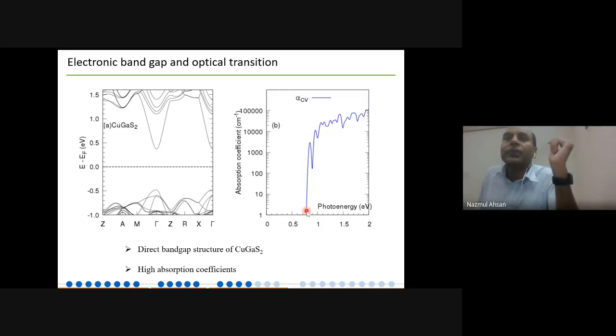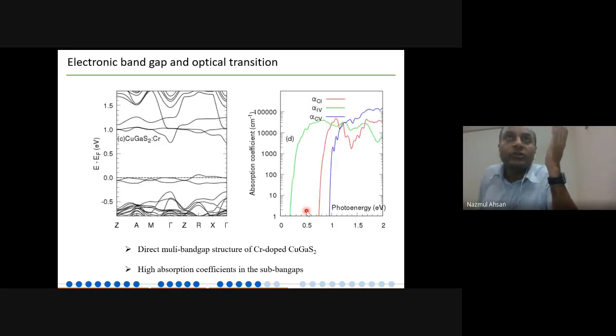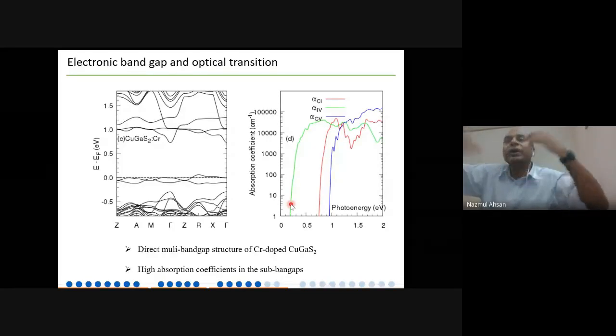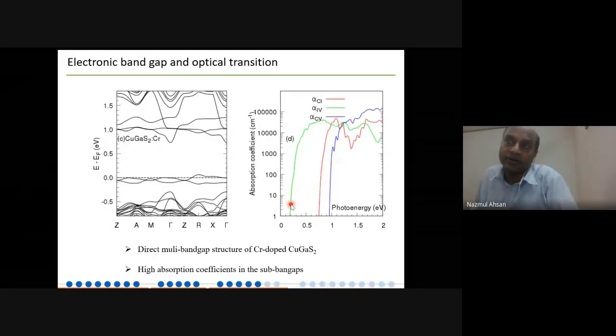then you can make a thin solar cell. But now if you dope your copper gallium sulfur by a little bit of chromium, now you see that you have three band gaps. This is again calculation, and all of them show very rapid rise in the absorption coefficient. And they have very similar strength of the absorption coefficient. So it tells that for the two-step photon absorption, your absorption should be matched to make the most of the photon to electrical conversion. And this is very good news. Then this is our calculation.